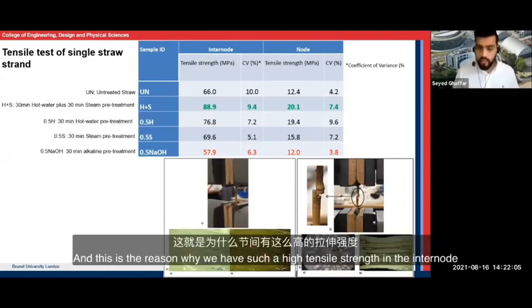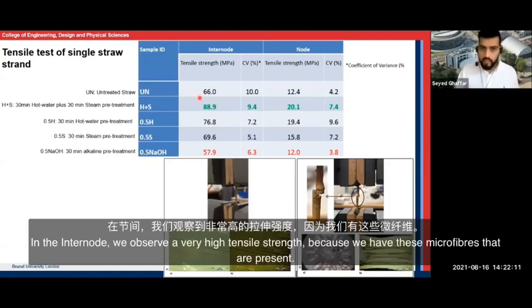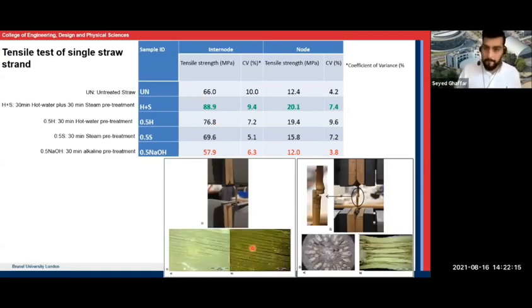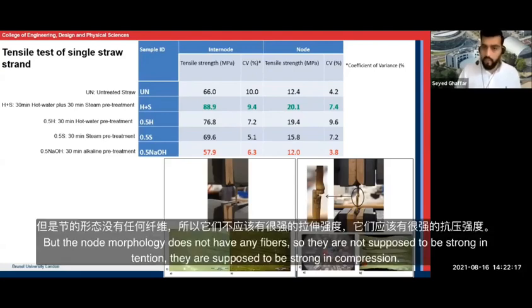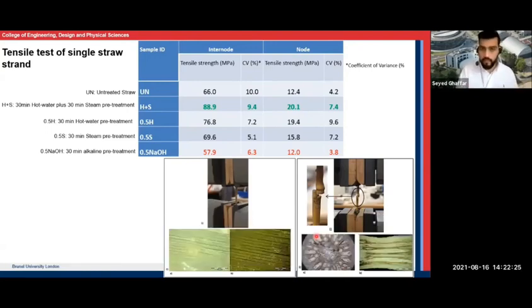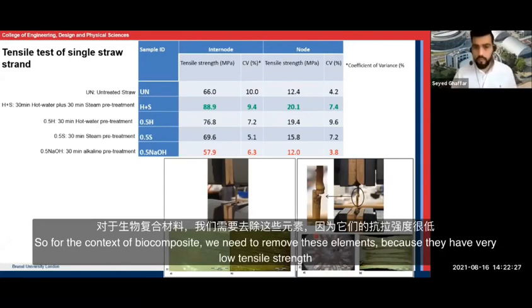And this is the reason why we have such a high tensile strength in the internode. We observe a very high tensile strength because we have these microfibers that are present. But the node morphology does not have any fibers, so they are not supposed to be strong in tension. They are supposed to be strong in compression. So for the context of biocomposite, we need to remove these elements because they have very low tensile strength.